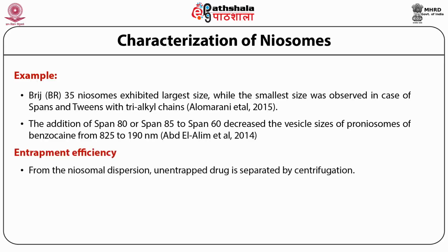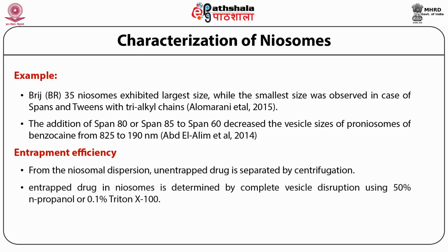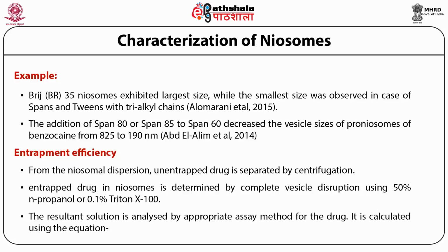From the niosomal dispersion, unentrapped drug is separated by centrifugation. The entrapped drug in niosomes is determined by complete vesicle disruption using 50% n-propanol or 0.1% Triton X-100. The resultant solution is then analyzed by an appropriate assay method for the drug.